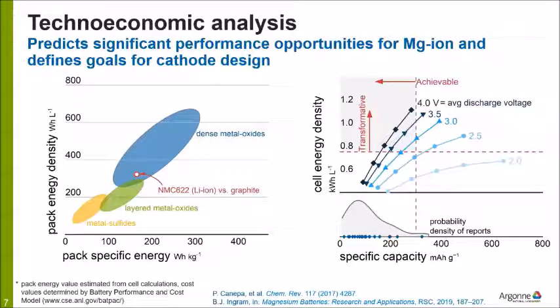On the right side, we see a plot which compares the specific capacity of the cathode and then the resulting cell-level energy density of the system. And you can see that voltage is a very important parameter.